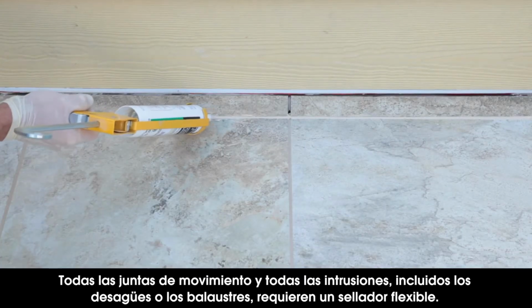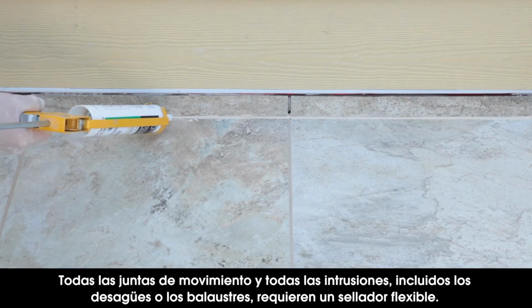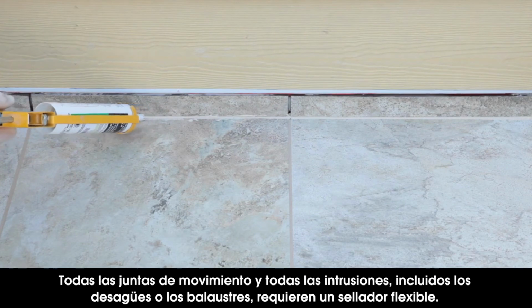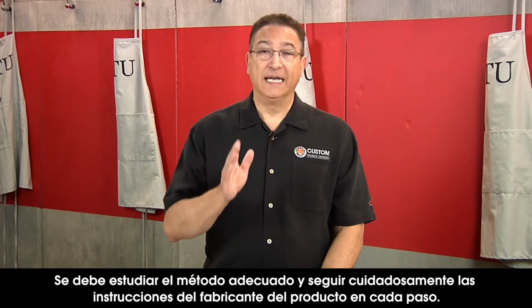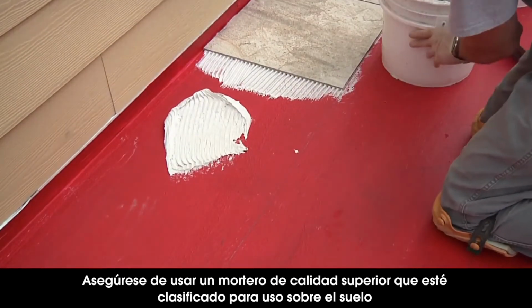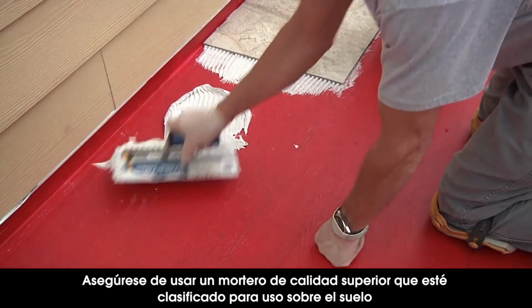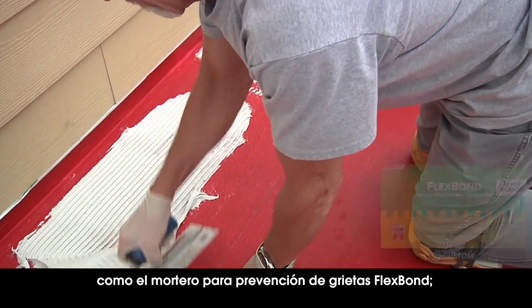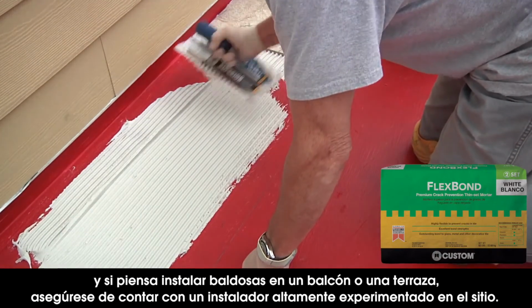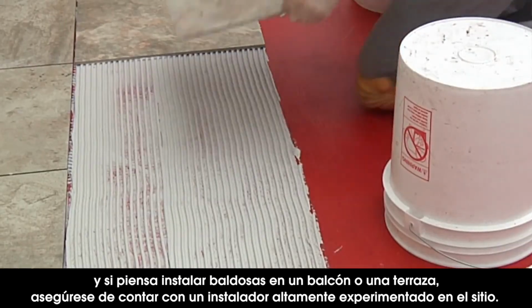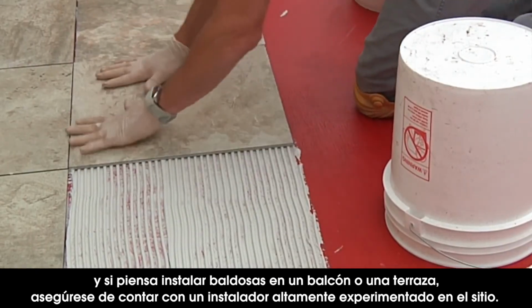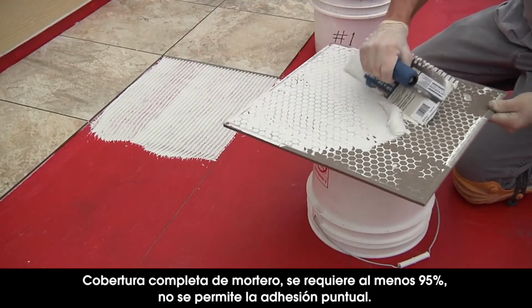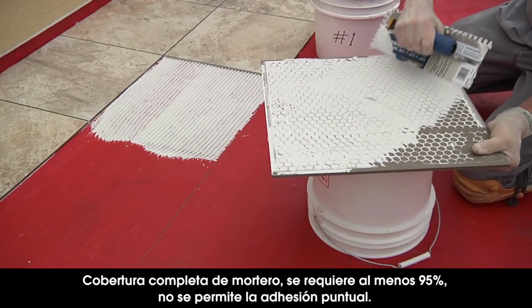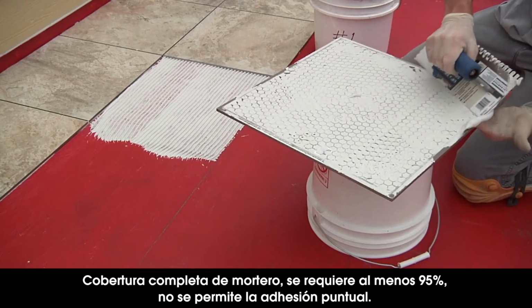All movement joints, any intrusions, including around drains or balusters, require a flexible sealant. So study the appropriate method and follow the product manufacturer's directions carefully in each step. Be sure to use a premium quality mortar that's rated for above ground use, like FlexBond crack prevention mortar. And if you're going to tile a balcony or deck, make sure you have a highly experienced installer on the job. Full mortar coverage, at least 95%, is required. No spot bonding is allowed.